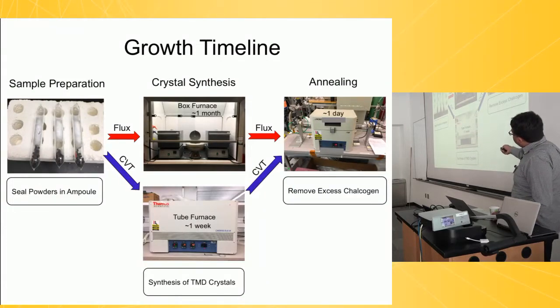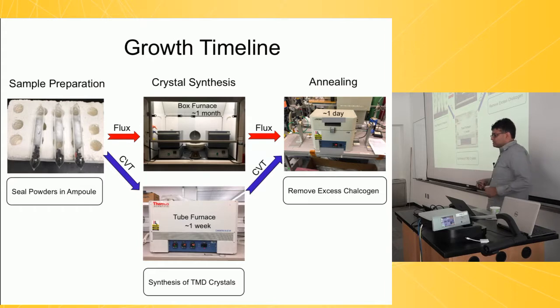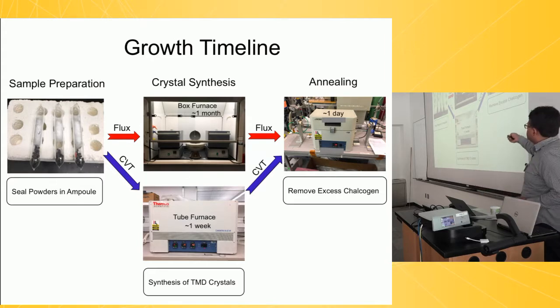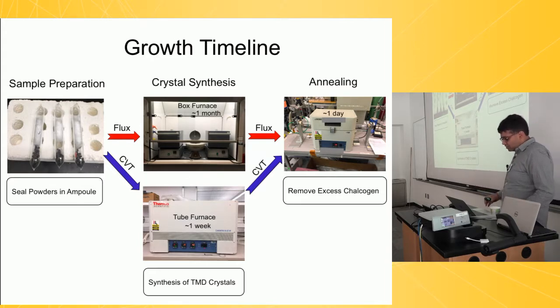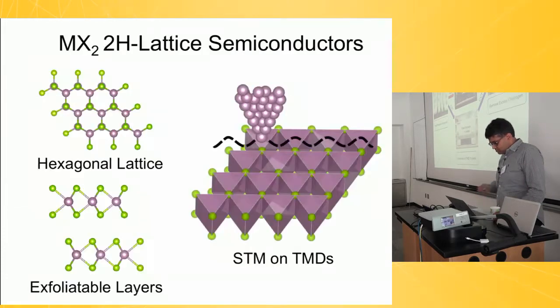So a little bit more about the sample growth. The CVT process typically takes on order of a week to do if you want to do a good job, make the highest purity crystals, whereas the flux method typically takes about a month or a couple of months. So if you're a company, they don't really like to do this because it takes a long time. You can grow fewer crystals.